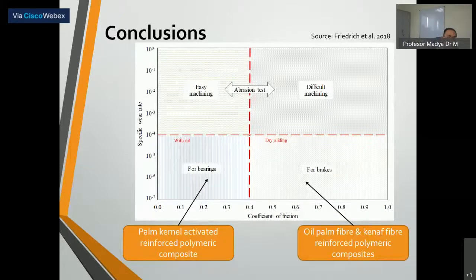Okay, as a conclusion, this map is from Friedrich et al. 2018. The map is of the specific wear rate and also the coefficient of friction. And we can see that this is the dry sliding. With oil, the applications for bearings, bearings need the coefficient of friction less than 0.4, and the specific wear rate must be less than 10 power of negative 4. And if the wear rate is larger than this value, and the coefficient is larger than 0.4, the suitable application for this material is for the brakes.